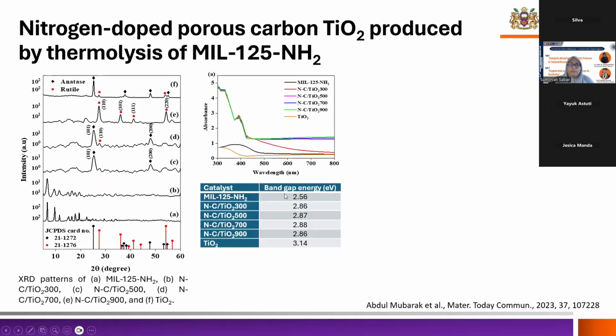So this is the band gap energy of the material of the MOF before and after calcination. So you can see that the band gap energy of the MOF actually increases, okay, because it's being transformed into titanium dioxide, but the titanium dioxide has a much larger band gap energy as compared to those that we obtained from the thermolysis of the MOF.